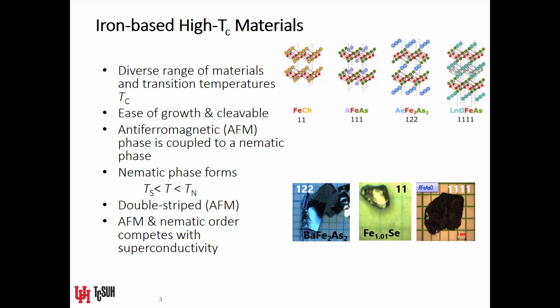In addition to the ease of growth, there's the cleavable nature of the iron-based samples, which enables people to put the samples into an experimental chamber, such as a vacuum chamber, then cleave the top surface quite easily to expose a relatively clean surface. The superconductivity occurs in close proximity to some type of antiferromagnetically ordered phase. So in the iron-based superconductors, magnetism and superconductivity, as I will show, are closely positioned within the overall phase diagram of these materials. Also closely coupled to the antiferromagnetic phase is something known as the nematic phase.